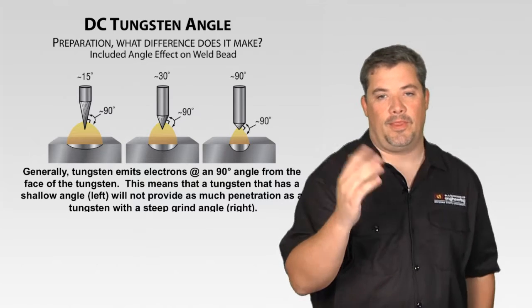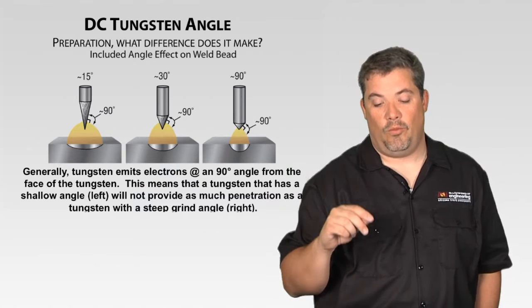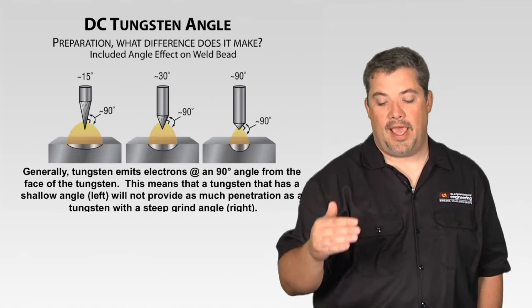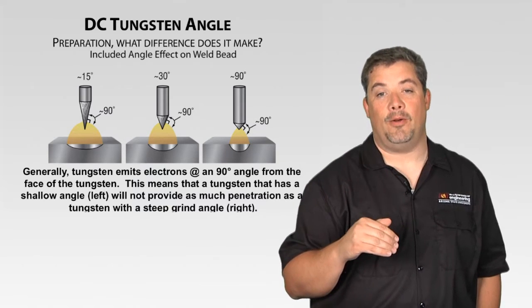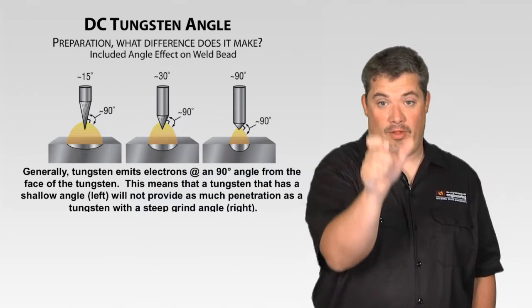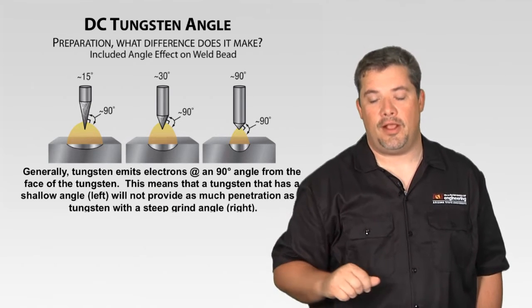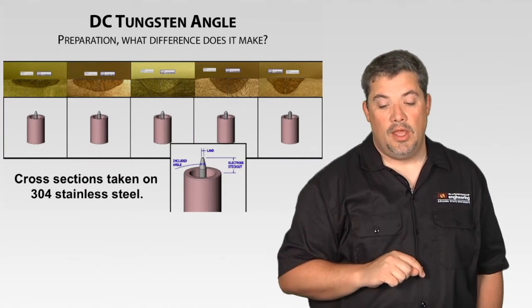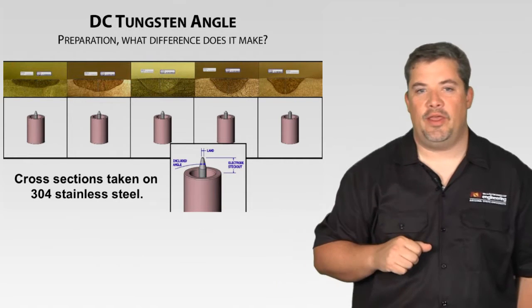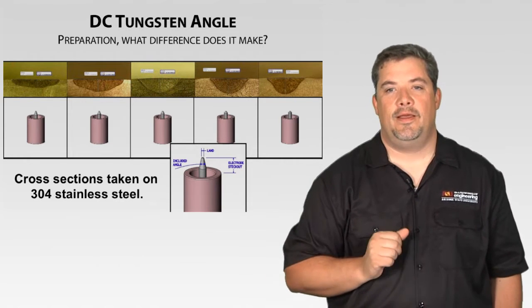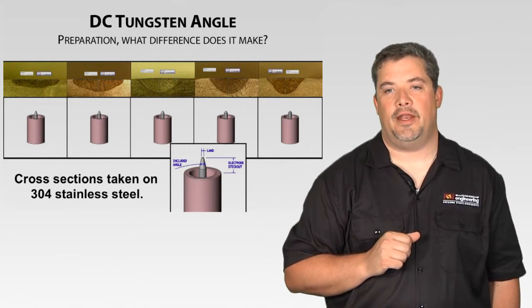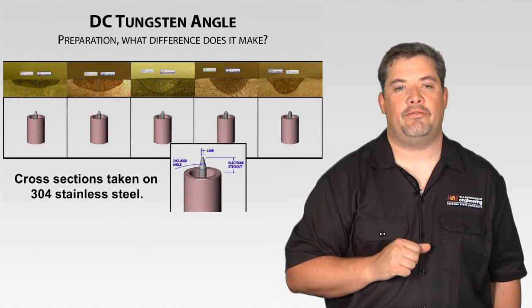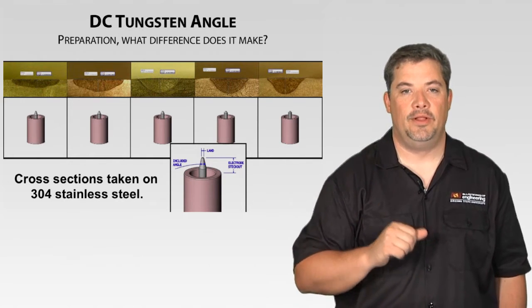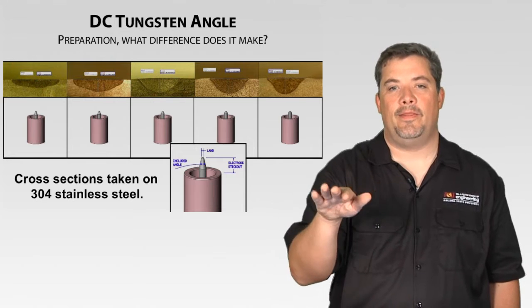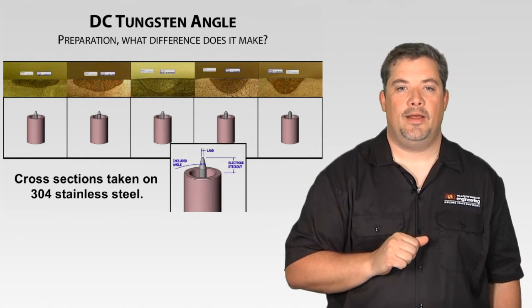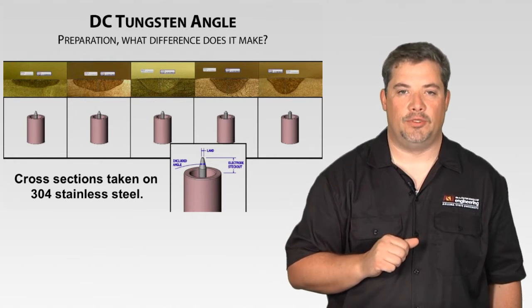So this is a great illustration of why that angle makes a difference. And blunting it back, you could think about it almost makes it even tighter than that 90-degree included angle will give you. There's an illustration, not the greatest of images, but you can see on the right is like a 90-degree included angle, on the left is like a 15-degree included angle, and you can see the shape that the weld bead made when those angles were changed.